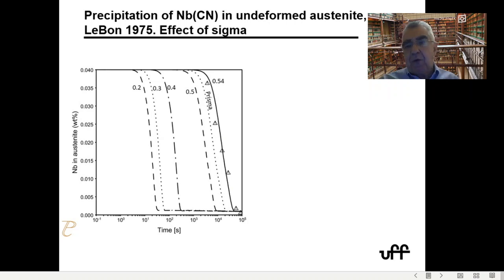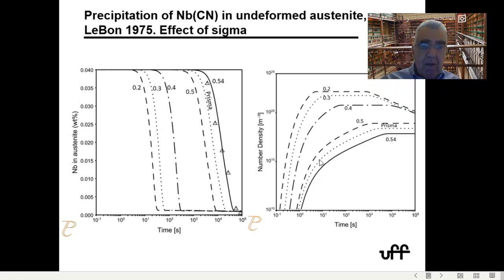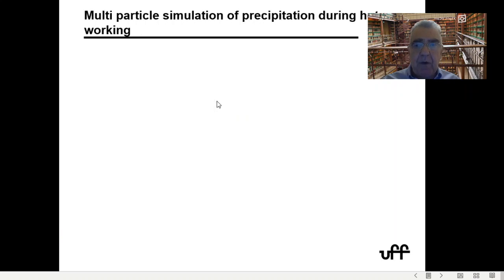But keep in mind that when you do this, it's not just changing this one parameter, niobium in solution. I mean, you're changing dramatically the number density of particles too. So if you change the interfacial energy that you're trying to fit your model, the number density changes, the size changes, everything changes. So it's very, very dangerous to go on just fitting this number like if it was a fitting parameter.